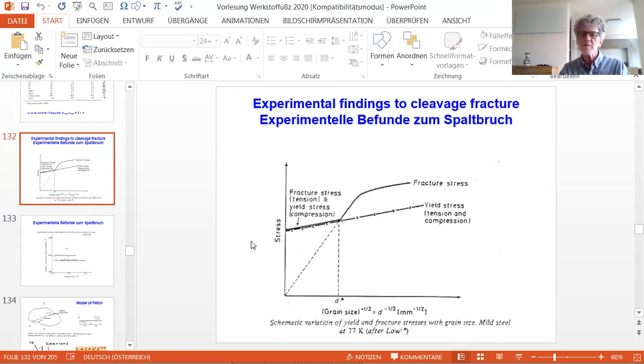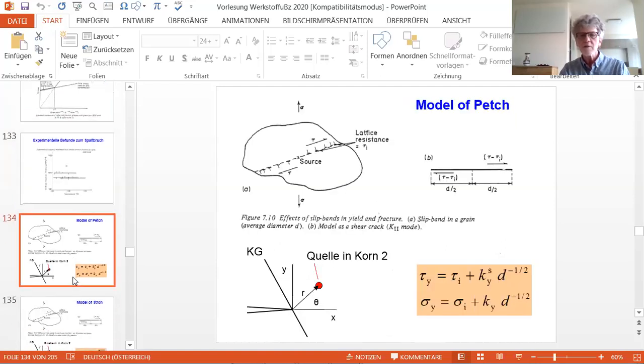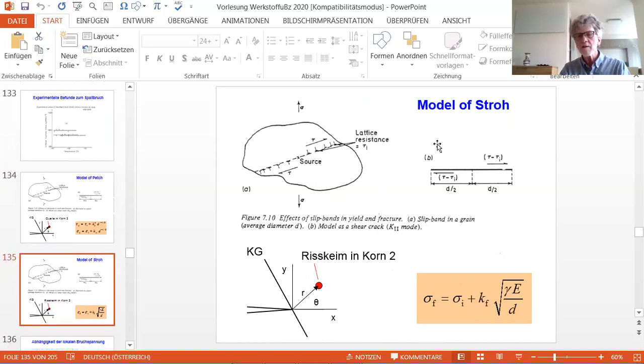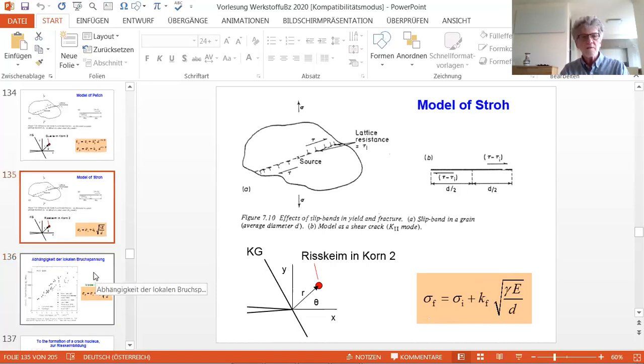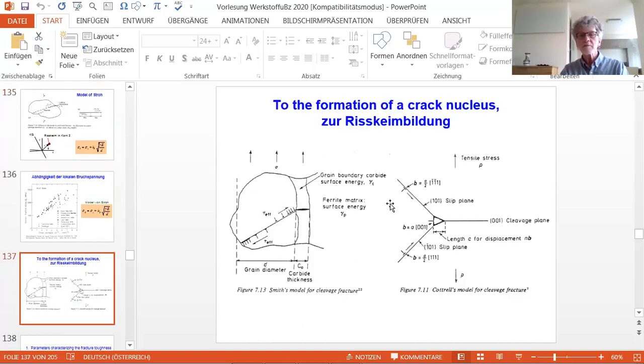For example, we found that the stress at which cleavage fracture occurs in a tensile experiment depends on the grain size of the material. Then we discussed the Hall-Petch model, which describes the dependency of the yield strength on the grain size. Similarly, the model of Stroh can describe the variation of the fracture stress for cleavage with grain size. And finally, we discussed a mechanism to form a crack nucleus, a mechanism of Risskeimbildung.